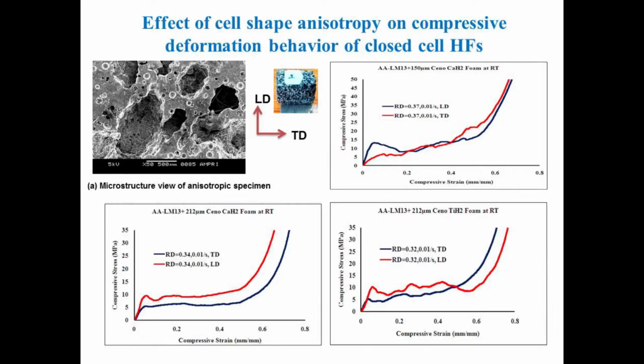And we have done some fundamental study on how the orientation of the cells affects the strength of the foam materials. And as I was telling, if the foam is used as the core for sandwich panels, for the same bending stiffness you can reduce the weight compared to steel. If you use the foam core sandwich panel for the same bending stiffness, the weight will be reduced by 50%. And in case of aluminum sheet, if you use the foam core sandwich panel, you can reduce the weight by 40%. So there is huge scope for using this aluminum foam in sandwich panels.